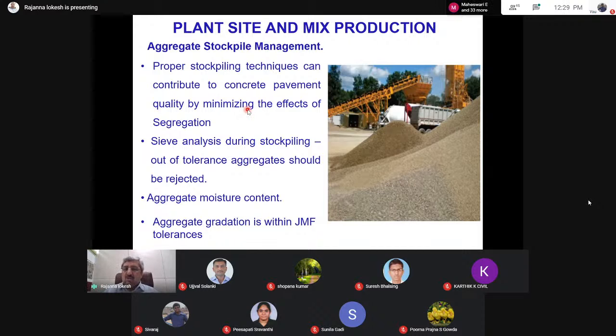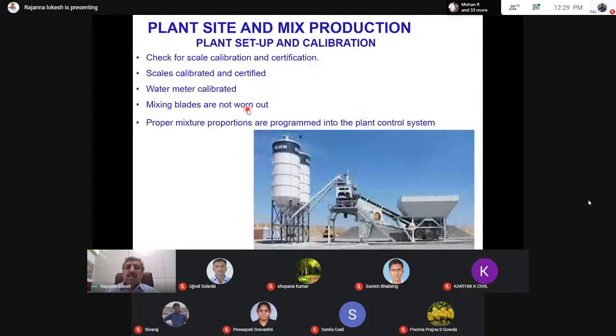Sieve analysis shall be carried out at the start of the day's work. Moisture in the aggregate as well as in the sand can have an impact on your water cement ratio. So it is all the more important for you to check the moisture content before the start of the work. So this is a setup of a batch mixing plant. It is important to calibrate this batch mixing plant because most of the time we are working on a weight basis. So it is important to calibrate each equipment before it is used for weighing.